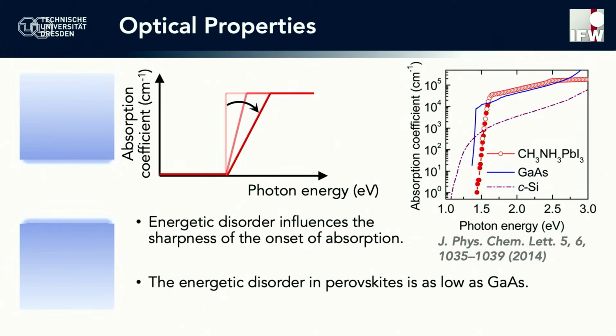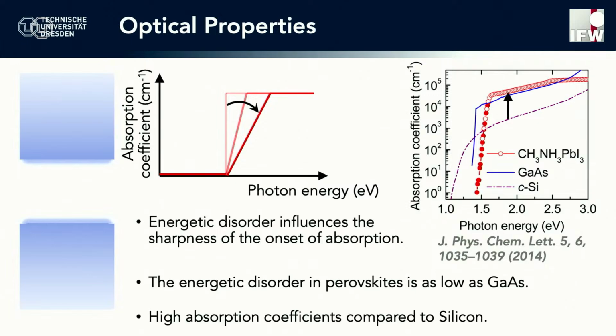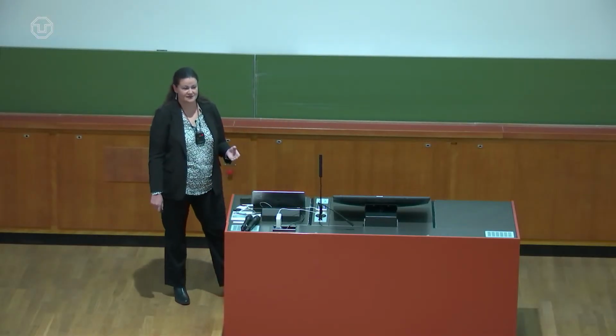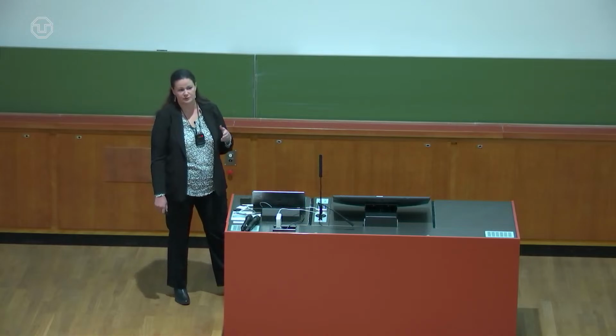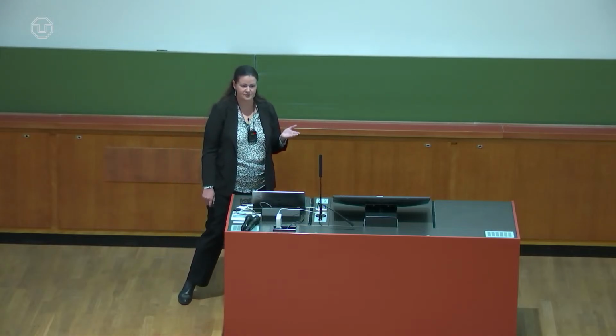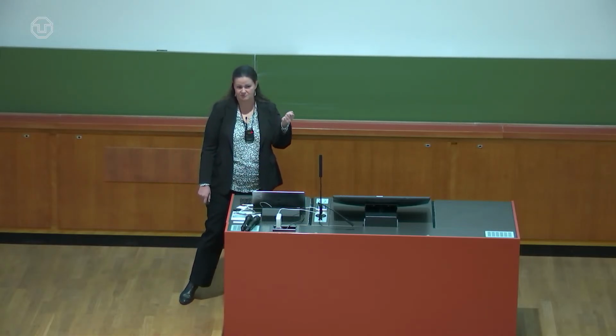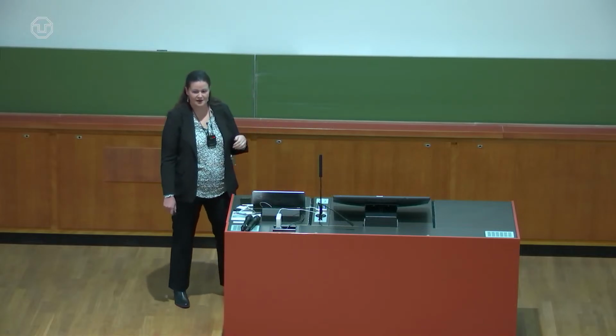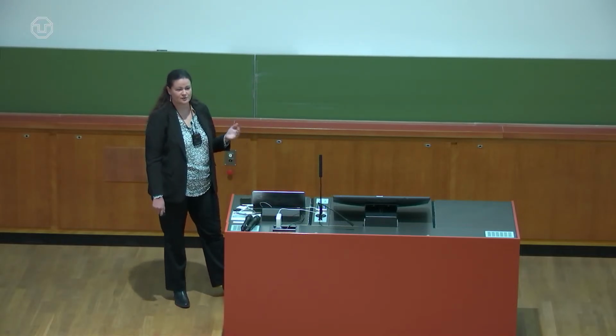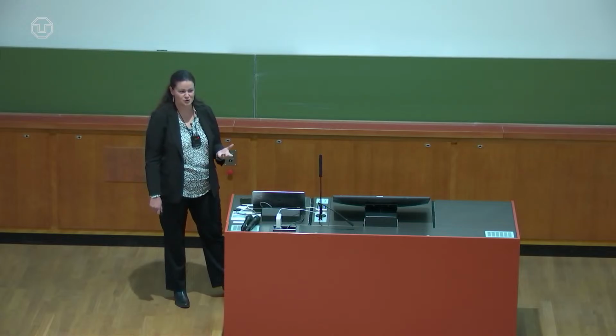Another important point is to look at the actual intensity of this absorption coefficient, how high it is. And you can see that the absorption coefficient in perovskites is significantly higher than that of silicon. Of course, the physicists and engineers in the room know exactly why, but the outcome of that is that while a silicon solar cell will typically be a couple of hundred microns, so essentially as thick as maybe a postcard, a perovskite solar cell can be a factor of 1,000 thinner because it absorbs light so well.